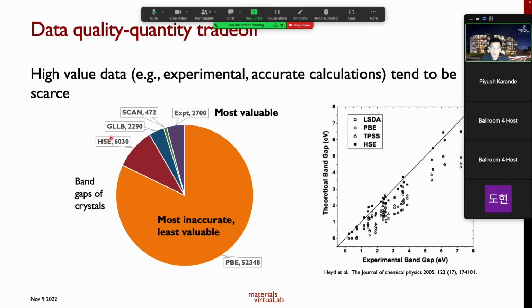Now we can do more expensive HSE calculations, but because HSE calculations are so expensive, the data set sizes are much smaller. And for experimental data, it is even smaller, right? There are only about 2,700 band gaps that we have found in the literature. And of course, these smaller data sets are what we actually want to predict. There's no use predicting the most inaccurate data point, even if we can predict it to very high precision, right?